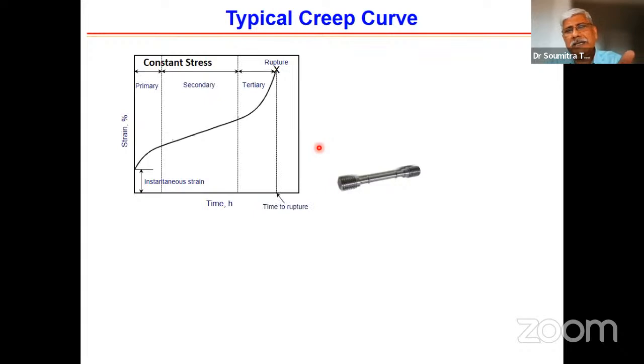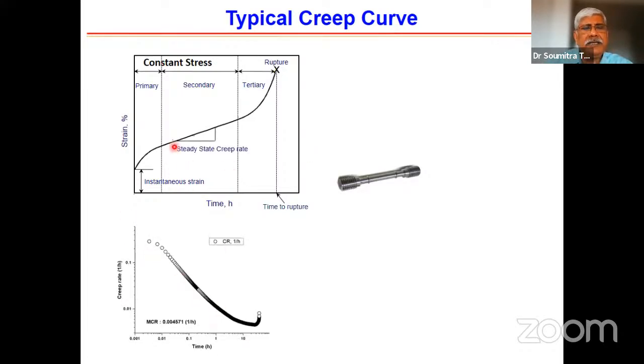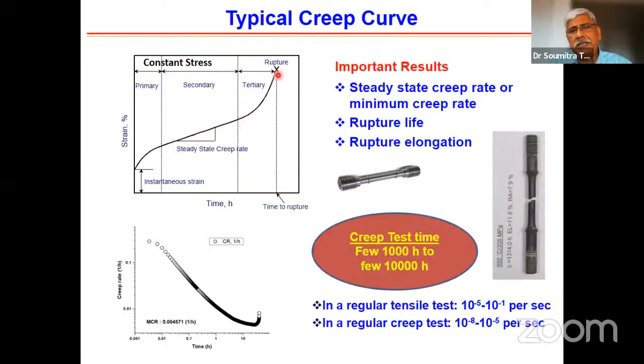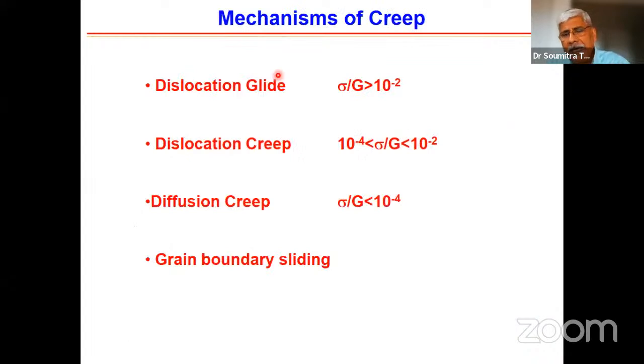So creep, as you know, is a very deleterious process for components and structures that are at high temperature, all your boilers, turbines, etc., where the creep rate initially decreases, of course, but the creep damage as a function of strain increases, and then ultimately it leads to failure. There are established procedures of doing a creep test, but the mechanism of creep is primarily through dislocations, by dislocation glide or dislocation creep or diffusion creep, depending upon the stress level that you have and the temperature. And of course, ending with grain boundary activity, sliding, cavity formation, etc., leading ultimately to failure.